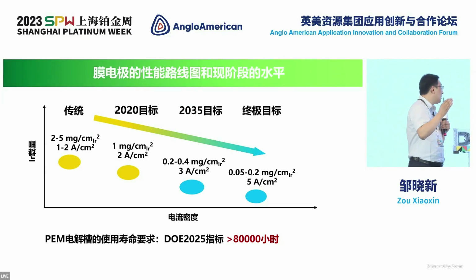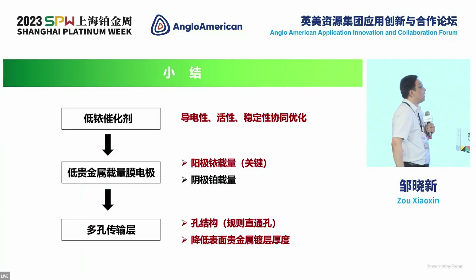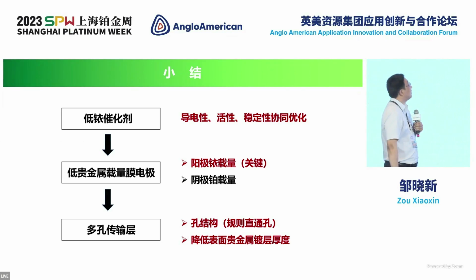In addition to loading requirement and activity requirement, for PEM electrolyzer, there is an indicator for life, which is around 80,000 hours. Be it in China or outside China, we haven't seen any reports of PEM electrolyzer that is even near the target of 80,000. Most of the products are in the range of thousands of hours. So for low loading, high activity, and long life PEM electrolyzer, there's still a long way to go. We have a lot to do in order to develop such a catalyst.